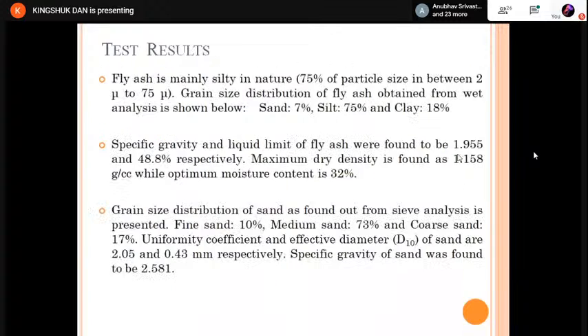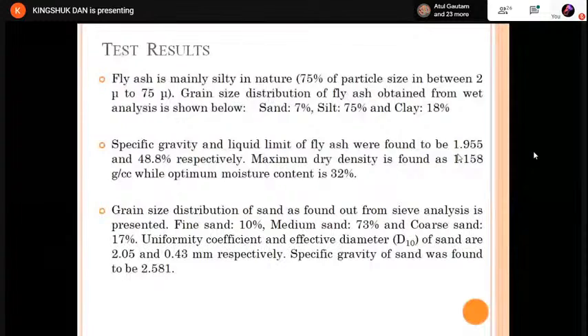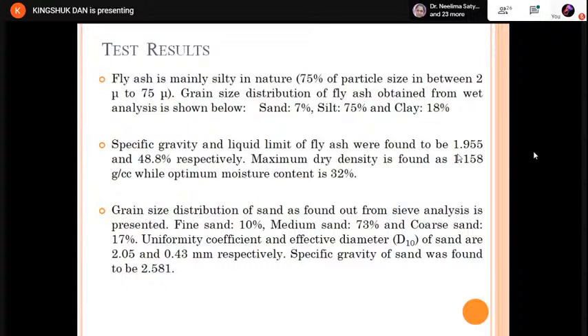Now from the test results, you can see fly ash is mainly silty in nature. 75% of particles are between 2 microns and 75 microns, and specific gravity test, Atterberg limit test, and Proctor compaction tests are also done. The maximum dry density is observed as 1.158 gram per cc, while optimum moisture content comes out as 32%. And simultaneously, grain size distribution of the sand which is used is also done here, and you can see the different percentages of the sand. From the grain size distribution, we have calculated the uniformity coefficient and effective diameter values.